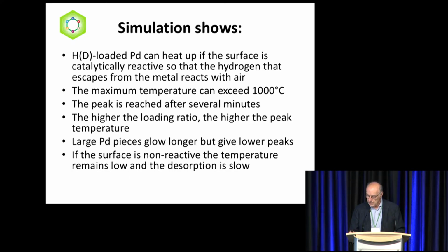So the simulation shows that hydrogen or deuterium-loaded palladium can heat up if the surface is a catalytic surface. The maximum temperature can exceed 1000 degrees C and more. The peak is reached after several minutes, and this is important. You are going to understand why in a minute. The higher the loading ratio, the higher the peak temperature, and large pieces glow longer but at a lower temperature. And if the surface is non-reactive, the temperature remains low and the desorption is slow.